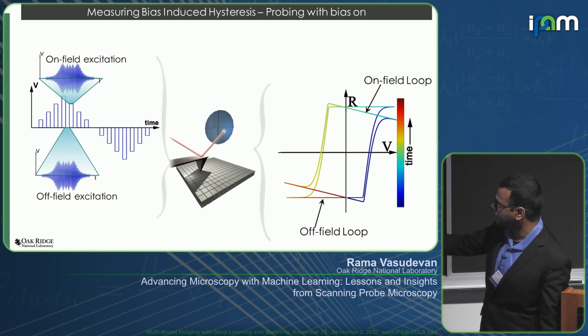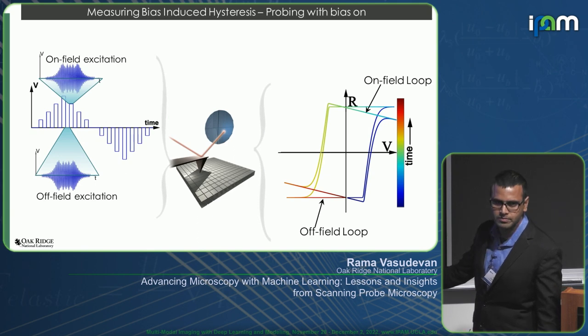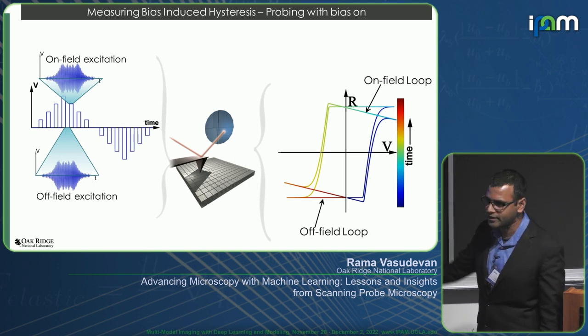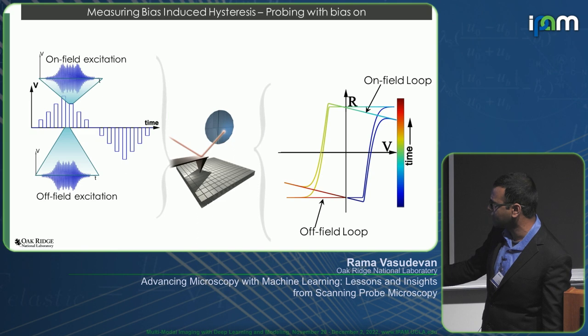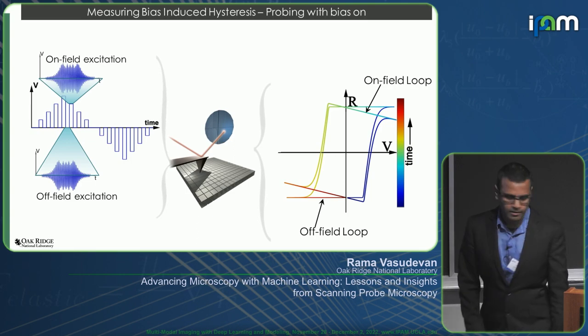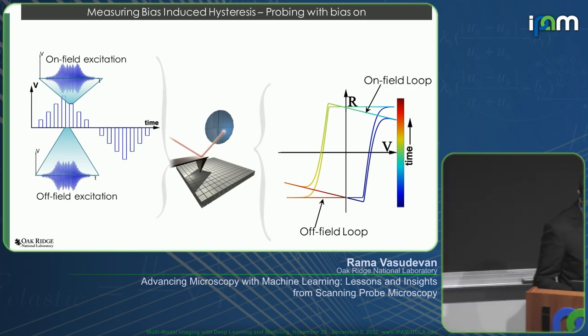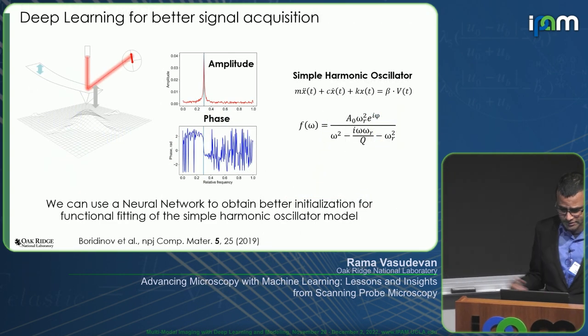And so for a ferroelectric material, this actually returns you the hysteresis loop. This is analogous to ferromagnetic materials, where you get similar hysteresis loops, but we can do this at the nanoscale, and so we can build up pictures of how the material is switching over nanometer-sized samples, or tens of nanometer samples.